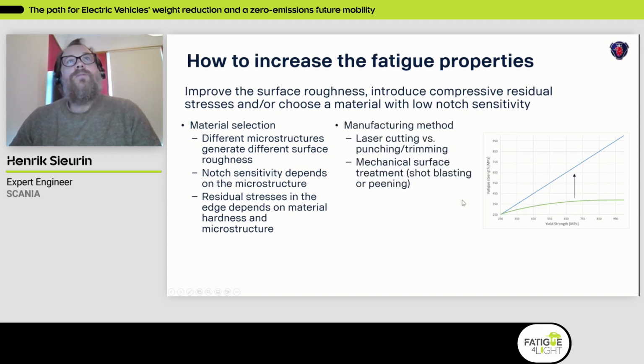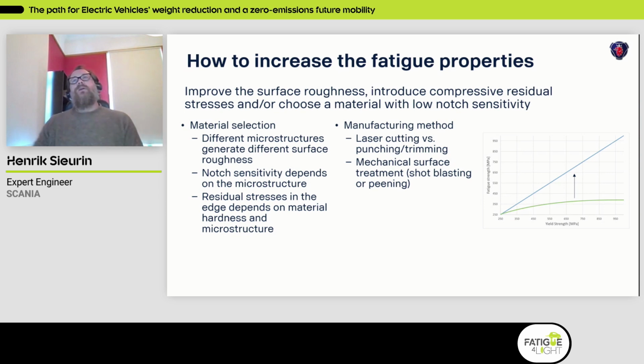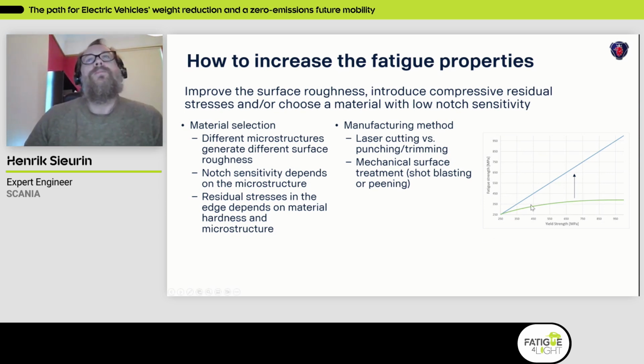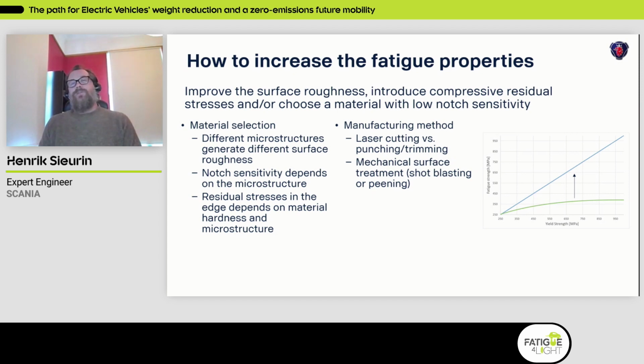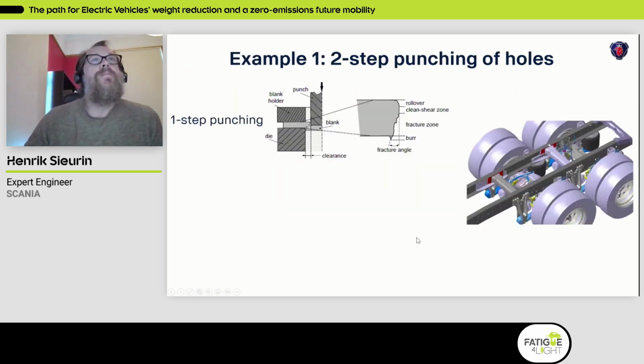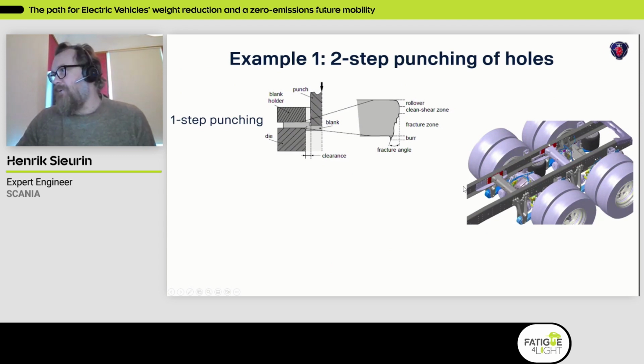Another way to do this is to work with the manufacturing methods. Laser cutting, for example, gives a much cleaner surface with better roughness, and you might even introduce compressive residual stresses at the same time. And you can also introduce mechanical surface treatment like shot blasting or peening. This has a combined effect. First, you introduce compressive residual stresses, but you can also improve the surface roughness and round the corners and so on.